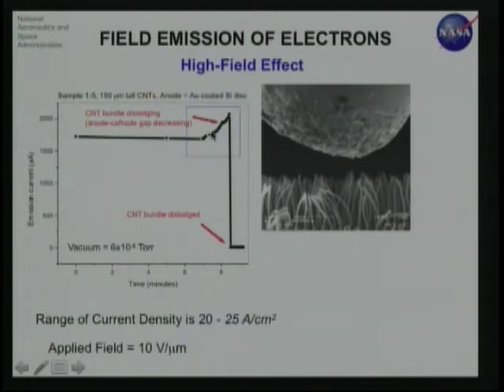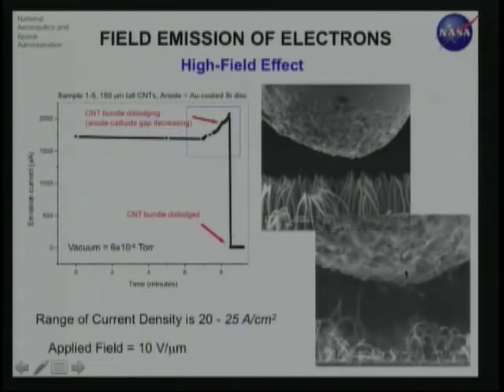You have a constant voltage, and then at some point it starts to increase, and then you have a drop in the current. That's because at the end, there's nothing left underneath the probe itself. It's all removed and dislodged from the substrate and pulled up.